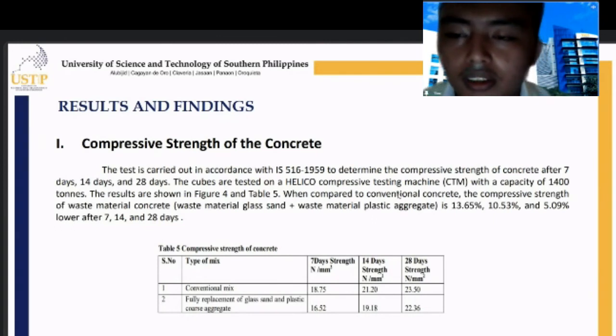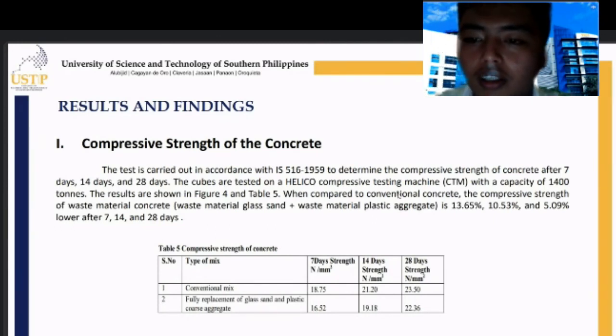I will discuss the results and findings of the study. For compressive strength of the concrete, the test is carried out in accordance with IS 516-1959 to determine the compressive strength of concrete after 7 days, 14 days, and 28 days. The cubes are tested on a compressive testing machine with a capacity of 1,400 tons. The results are shown below on the table. When compared with the conventional concrete, the compressive strength of waste material concrete is 13.65%, 10.53%, and 5.09% lower after 7, 14, and 28 days.